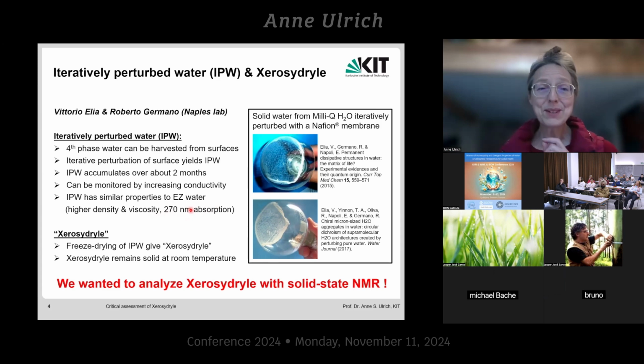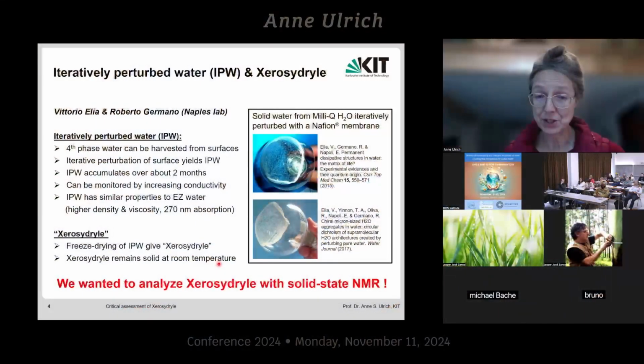Now, the most curious point was when the Naples team then lyophilized this harvested water, and they call the dry residue Xerosydryle. In fact, this Xerosydryle is supposed to consist of just water molecules, H2O, but they are solid at room temperature. And that is really something very spectacular. You see here on these round bottom flasks, 2 examples that they have published in good journals, that they actually can harvest a residue from surfaces of various nature. And so when I came along to see these results, I was fascinated and wanted to do some solid state NMR analysis. That is because my team in Karlsruhe is a biophysics group.